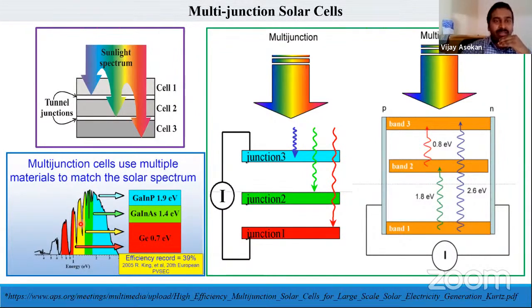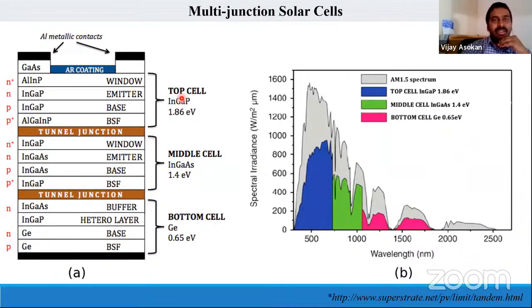So for example, if you see here, it has multiple materials with gallium indium phosphide, or gallium indium arsenide, or germanium. So it lies at 0.7 electron volt, 1.4 and 1.9. It combined everything, and the efficiency record at the time, in 2005 when such a multi-junction was established, was 39 percent efficiency. So there can be multi-junction or multi-band solar cells which have different energy bands. So it covers all the incident energies on different scales.